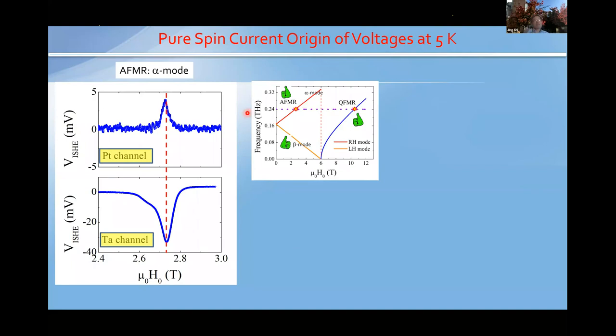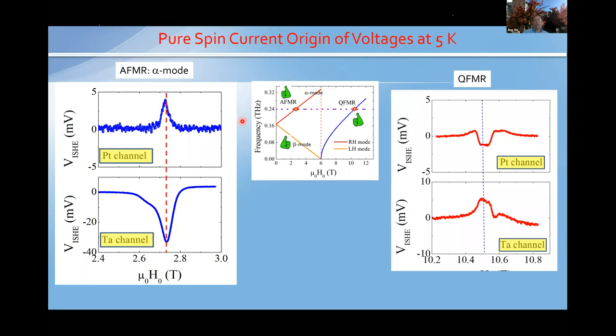Now, to verify this is indeed from a spin current, we switch the platinum channel to a tantalum channel. As I said earlier, we expect a sign change. Indeed we have this sign change in both channels, at exactly the same location of the field. The quasi-ferromagnetic feature has also been inverted when we switch from platinum to tantalum. So both signals are of spin current nature, and we do detect the inverse spin Hall voltage.